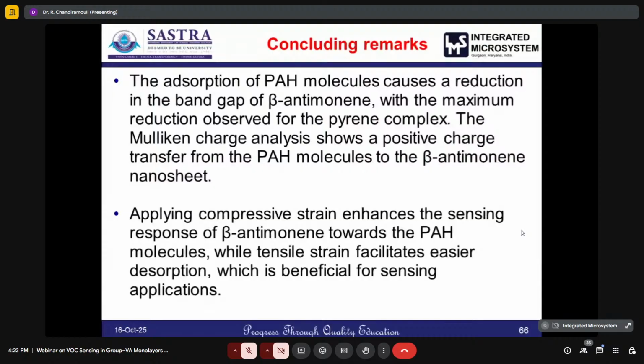And the concluding remarks: the adsorption of PAH molecules causes a reduction in the band gap of beta-antimonene, and the Mulliken charge analysis also shows a positive charge transfer from the PAH molecule to the beta-antimonene sheet. And the important thing is that upon applying compressive strain, it enhances the sensing response of beta-antimonene towards the PAH molecules, whereas tensile strain facilitates easier desorption of the PAH molecules, which is beneficial for a sensing application.